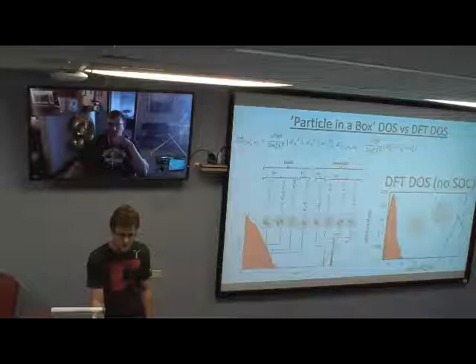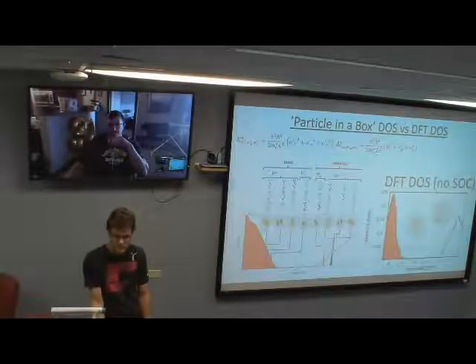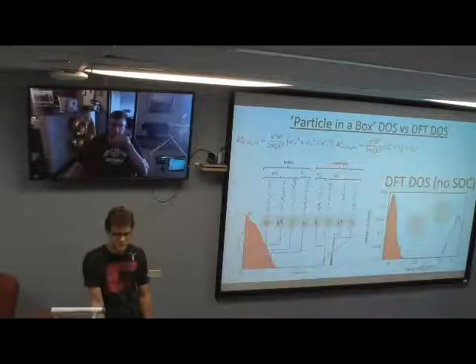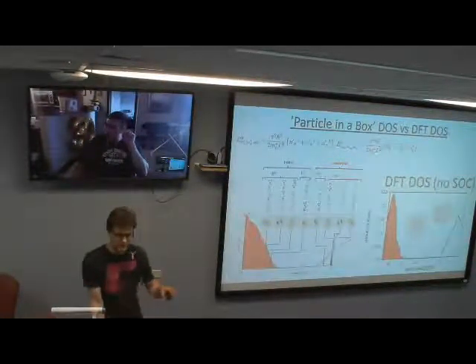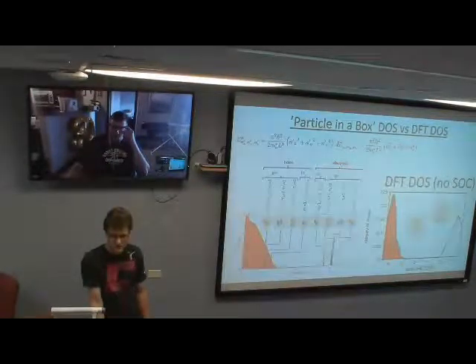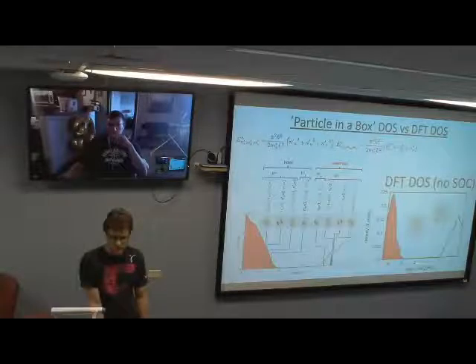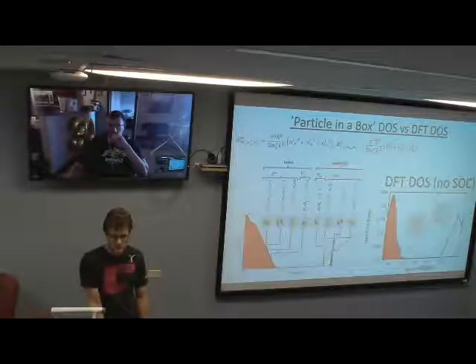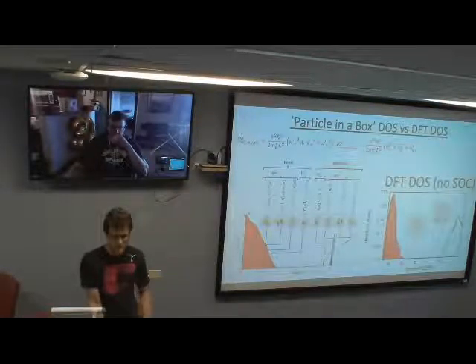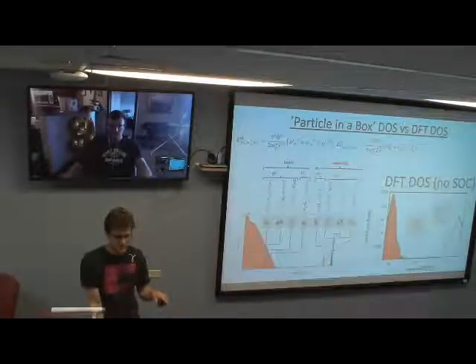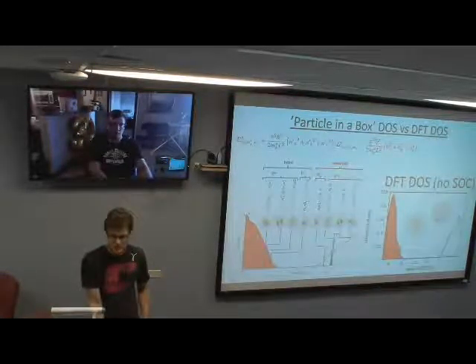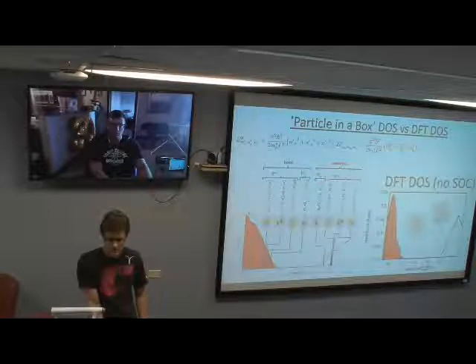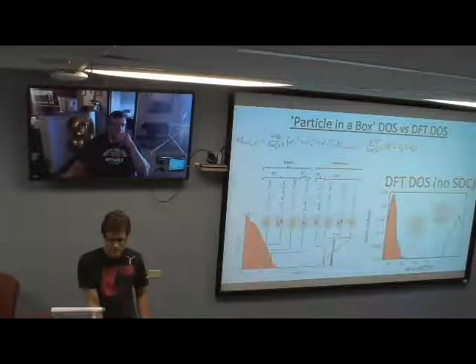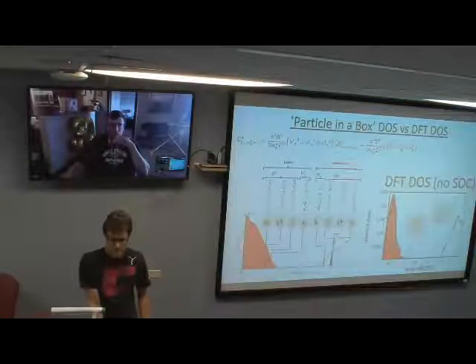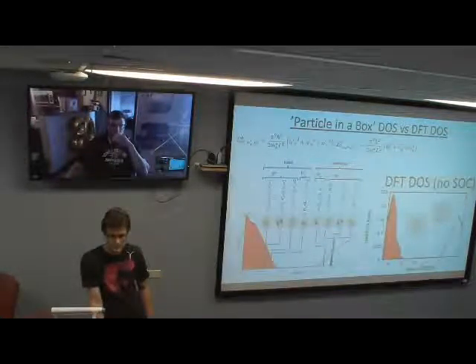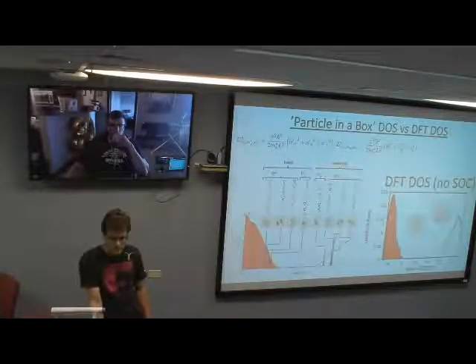So what we know from quantum mechanics: can you find the wave function outside the sizes of your box, if it's infinite box? If it's infinite, no. But in reality, you can. Which means you expect no appearance of your electronic wave function on ligands, if ligands are not really involved in your model, right? If your model is just the perovskite without ligands on the surface. But in your DFT calculations, and just intuitively, of course, we expect that the electronic cloud should be spread and not just be confined exactly inside the perovskite material, right? Mm-hmm. So which means that in reality your box is a finite size box.